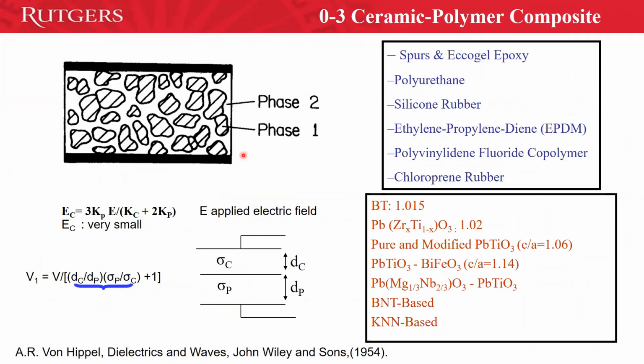Let me go back to, again, PZT particle polymer composites. One can put all kinds of polymer listed here, depending on their electrical connectivity. And then you can put a variety of filler material. BT and PZT were traditionally used, but then why not some other piezoelectric particles such as lead titanate, bismuth ferrite, and so on, and many others. But this type of composite is not easy to polarize.